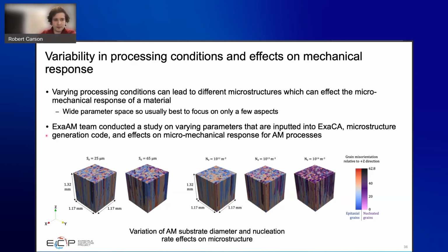Matt Rochigo, who's a member of the ExaAM team, led the study of varying the parameters for the microstructure processing conditions using ExaCA, and it generated a bunch of different microstructures. And I helped look at what the difference of the micromechanical response was from these varying microstructure conditions. During the study, he looked at varying the AM substrate diameter, so that's your base plates, grain sizes. And then he looked at varying the nucleation rates for your grains and how that affects the microstructure. So he got a lot of different microstructures depending on how the parameters were varied.